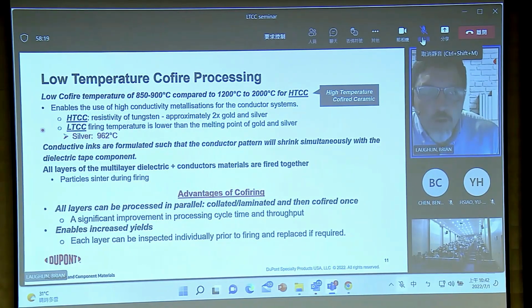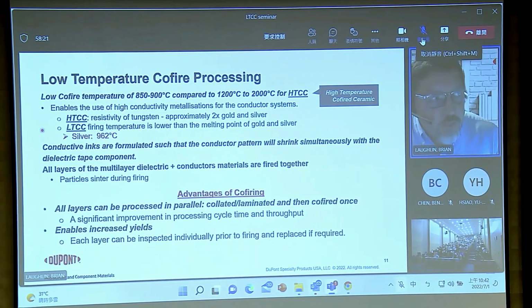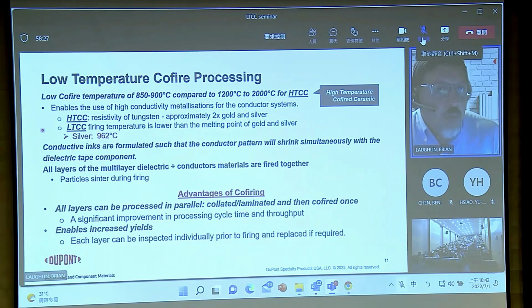All of that firing and the design of the tape and all of the conductors are all formulated together for compatibility, not just chemically, but in the way they all sinter. And so the conductive inks are formulated and matched to the particular product lines so that the conductor pattern will shrink simultaneously and in the same degree with the dielectric tape.